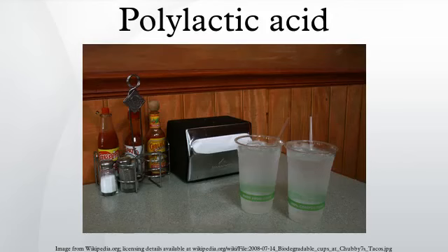Degradation. Amycolatopsis and Saccharothrix are able to degrade PLA. A purified protease from Amycolatopsis sp., PLA depolymerase, can also degrade PLA. Enzymes such as bromelain, pronase and most effectively proteinase K from Tritirachium album degrade PLA. Pure PLLA foams undergo selective hydrolysis when placed in an environment of DMEM supplemented with fetal bovine serum. After 30 days of submersion in DMEM plus FBS, a PLLA scaffold lost about 20% of its weight.